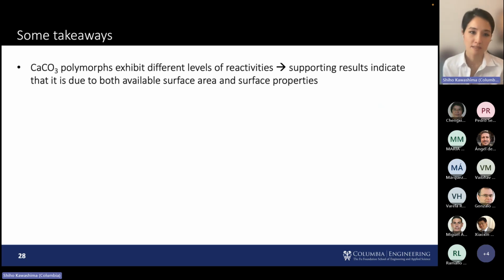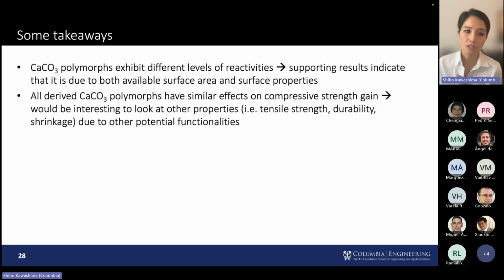So some key takeaways. Calcium carbonate polymorphs exhibit different levels of reactivities, or they can. And supporting results indicate that it's both due to available surface area, but also surface properties. All the derived calcium carbonate particles or polymorphs had a similar effect on compressive strength gain. So we didn't really capture any differences there, but it would be really interesting to look at other properties and also scaled up because the scaling matters. So interested in tensile strength, durability, shrinkage due to other potential functionality. So again, all these polymorphs look very different and they may introduce beneficial properties outside of compressive strength.